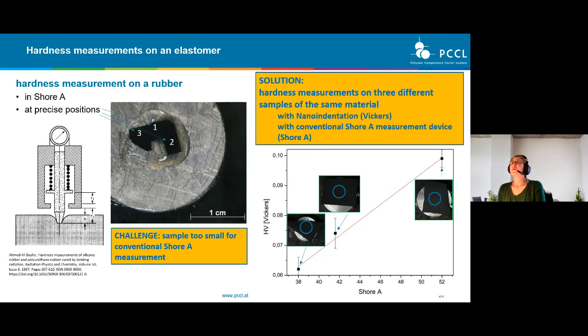Next, I want to show you some hardness measurements on an elastomer. We wanted to do hardness measurements on a rubber, in Shore A and at very precise positions. The challenge here was that the sample was too small for a conventional Shore A measurement device. As you can see here on the left side, the Shore A measurement device needs some space. And the solution with nanoindentation was we did hardness measurements on 3 different samples of the same material. First of all, with nanoindentation in Vickers, and second, with a conventional Shore A measurement device in Shore A. And then we did a regression line for these samples.